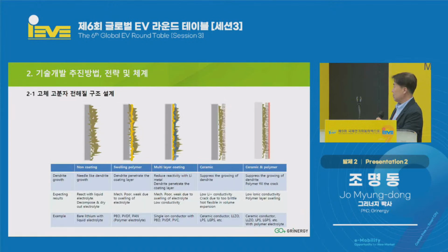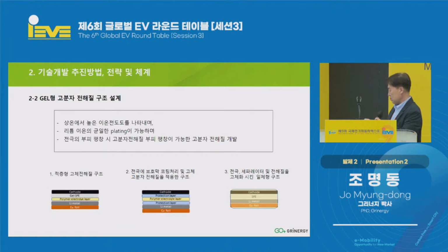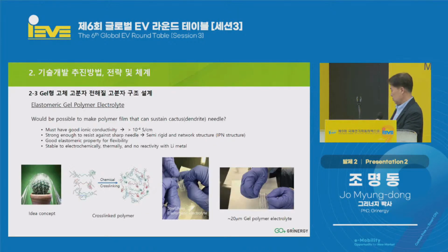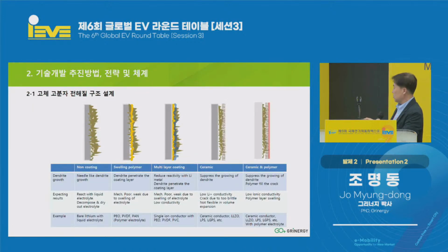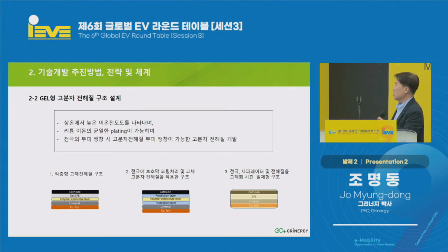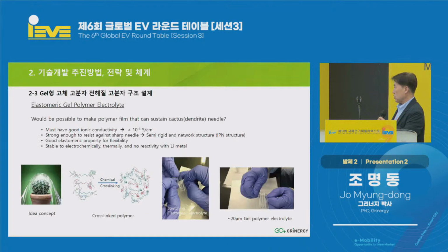So we presented that idea, and then we came up with a gel type of high polymer. But as the lithium grows, as I have shown before, as you can see here, the high polymer cannot suppress it. We need to come up with a way to suppress the growing of the dendrite. And we came up with the idea to design the solid polyelectrolyte structure. So we began the synthesis of that.